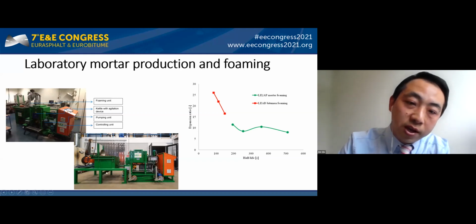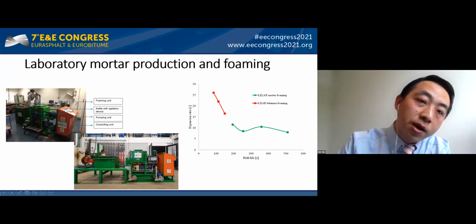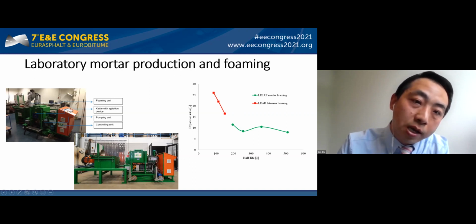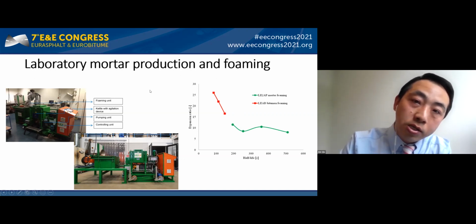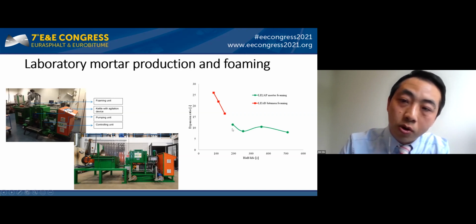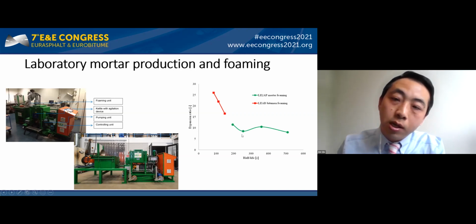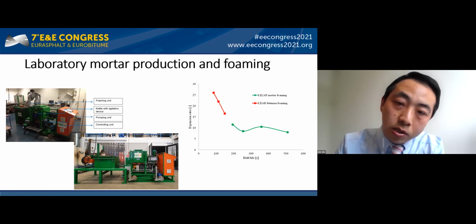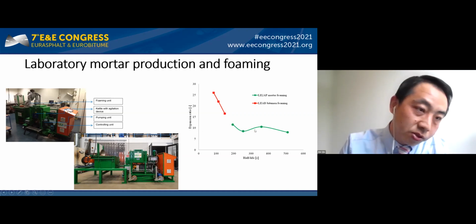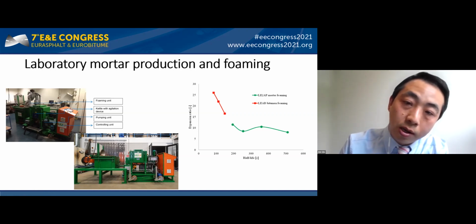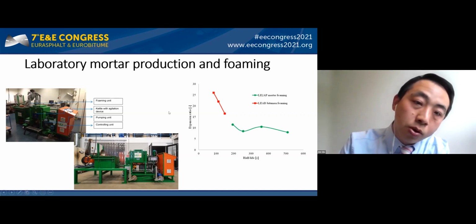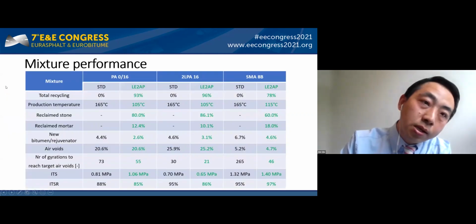This is a new format of that. With the dosing unit, you are able to form it at low temperature. In this case, the mortar that you formed has a temperature of about 110 to 120 degrees. And here you will see the expansion ratio of this formed mortar. It's about 10 on average, with a half-life of 3 to 4 minutes. It is very long, and it is a very good quality without settlement.